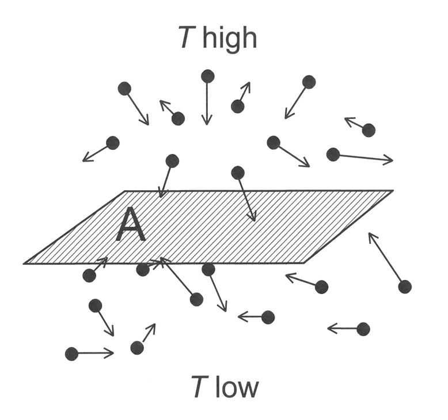For metals at low temperatures, the heat is carried mainly by the free electrons. In this case, the mean velocity is the Fermi velocity, which is temperature independent. The mean free path is determined by the impurities and the crystal imperfections, which are temperature independent as well. So the only temperature dependent quantity is the heat capacity C, which, in this case, is proportional to T. So K = K₀T, metal at low temperature,